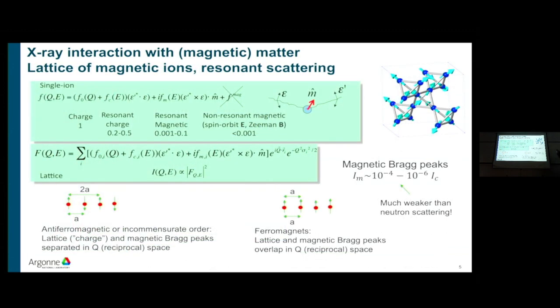So now that was one atom, and now we're interested in putting these atoms in crystals. And when you put atoms in crystals, you have crystallographic positions. There are symmetries that come into play, and the scattering from the different atoms either interfere constructively or destructively. You have to come up with what's called a structure factor. So you take these individual atom scattering amplitudes. Here I bundle the non-resonance and resonant charge with the resonant magnetic, with the different polarization factors. And you have this phase factor that sort of will tell you how the scattering from different positions in the lattice interferes with one another.